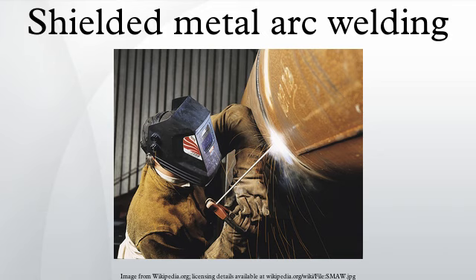Electrodes containing calcium fluoride, sometimes known as basic or low hydrogen electrodes, are hygroscopic and must be stored in dry conditions. They produce strong welds, but with a coarse and convex-shaped joint surface. Electrodes coated with cellulose, especially when combined with rutile, provide deep weld penetration, but because of their high moisture content, special procedures must be used to prevent excessive risk of cracking. Finally, iron powder is a common coating additive that increases the rate at which the electrode fills the weld joint, up to twice as fast.